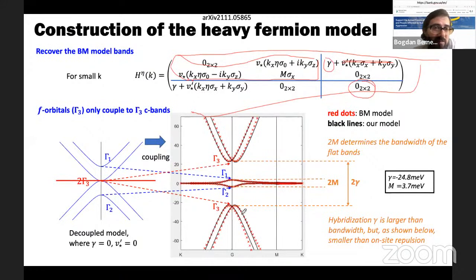So you might think, well, it might do a very poor job at fitting the band structure or the wave functions. Now this is how the band structure is fit. The red dots are the Bistritzer-MacDonald model. The black lines are our model. Now the fitting does get worse here at higher energies, but those higher energies are not where the physics happens. And we could actually improve that fitting by taking more terms than just linear terms in this model. But you can see how remarkably well this model does.